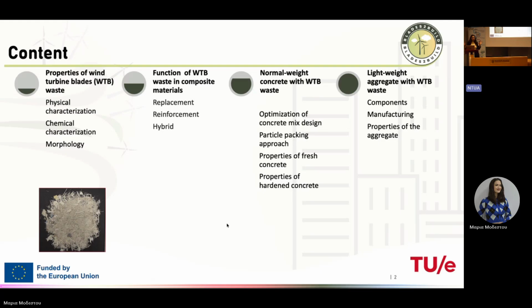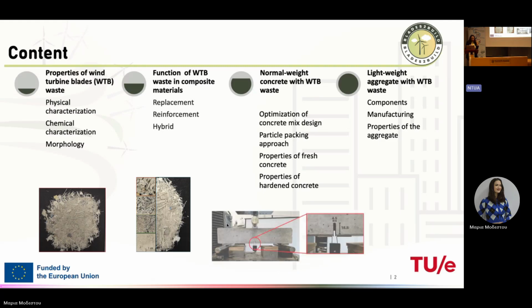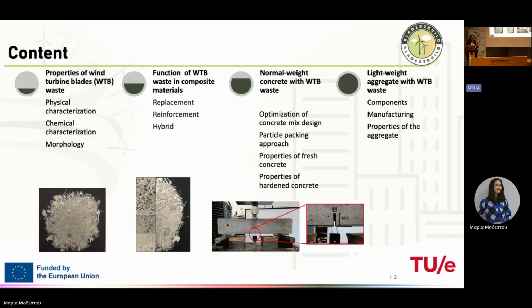So we receive the waste from zero up to 20, 60, 80 millimeters. It was not sieved on the lowest part, but the highest was limited. And we sieved it. It's also challenging to sieve this waste to get a size because it's heterogeneous, as you see. And we make use of it, as I said, in concrete. You will see some tests in detail. This is a semi-circular bending test, where we make a notch to test flexural strength and to see how cracks propagate, because we make the crack form in a specific place in this beam.